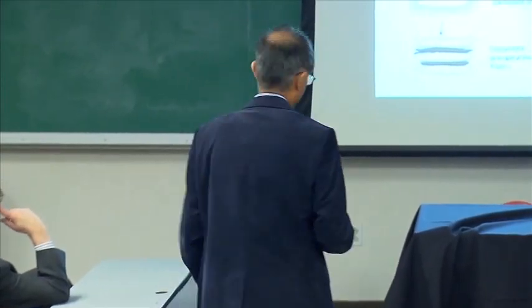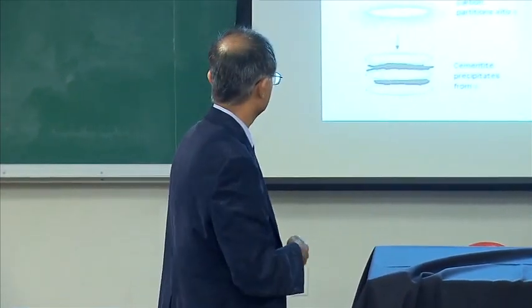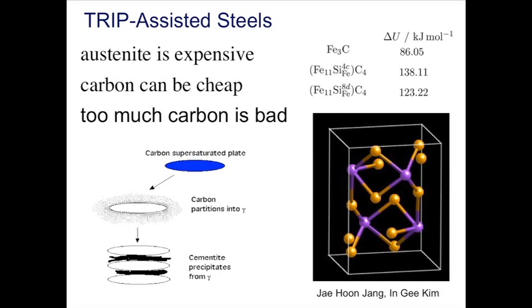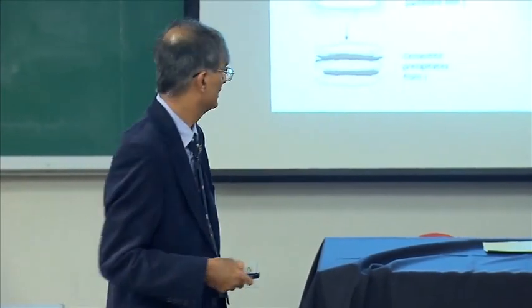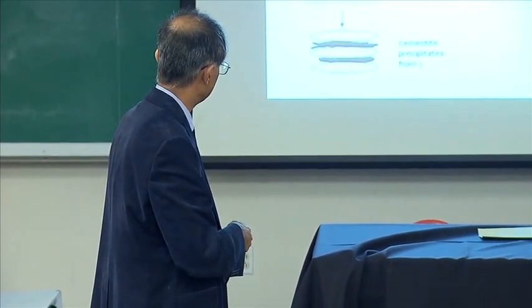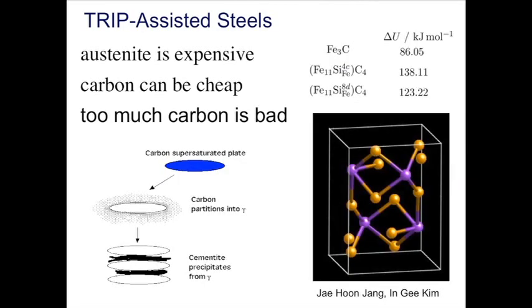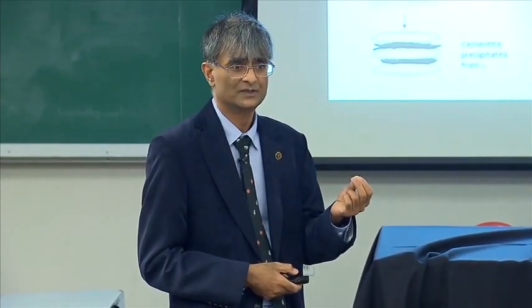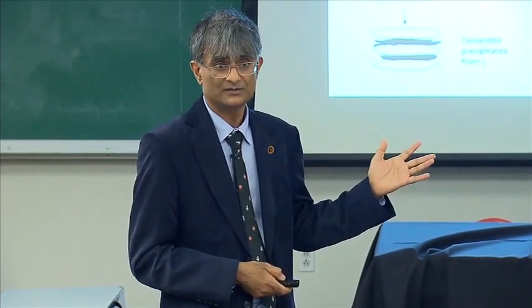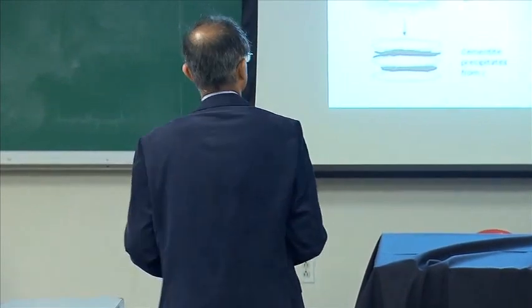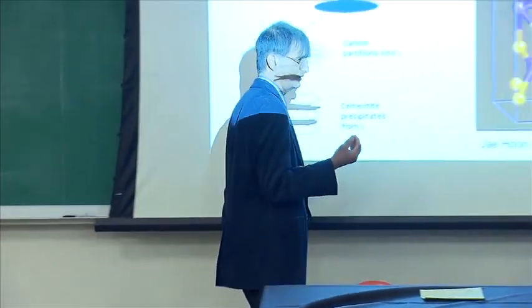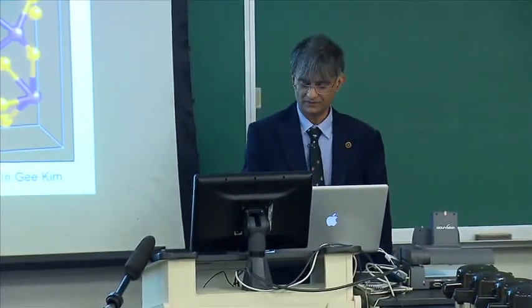Okay? So basically, it forms exactly like martensite, right? So it's a diffusionless transformation, but it's forming at a temperature where the carbon is mobile. So shortly after transformation, it escapes into the remaining austenite and then precipitates as carbides, iron carbides. But if we stop this reaction here, then we end up with a mixture of ferrite plates and carbon-rich austenite. And the way to stop this reaction is, this is the cementite unit cell, Fe3C. If I pull out an iron atom and substitute it with silicon, then you can see that the energy goes up dramatically. Cementite hates silicon. Okay? So if you add a small amount of silicon to your steel, then cementite will not precipitate in these circumstances. So the role of silicon is basically to allow us to produce austenite, which is rich in carbon, and not to lose the carbon by precipitating cementite.